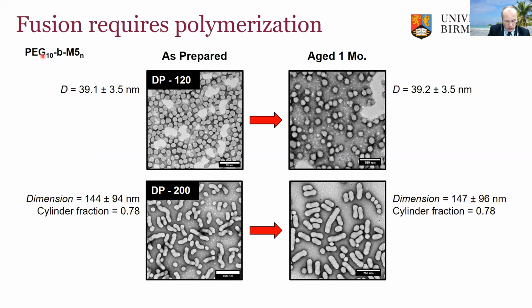So if you look, this is just for our PEG system, as I said, the DP 120 polymers as prepared, if we just leave them and age them for a month, they look exactly the same. So the constructs we're making are stable and don't undergo a morphology transition over time. And that's whether it's the starting spherical polymersome or our tubosomes, after a month of aging they're indeed very similar.